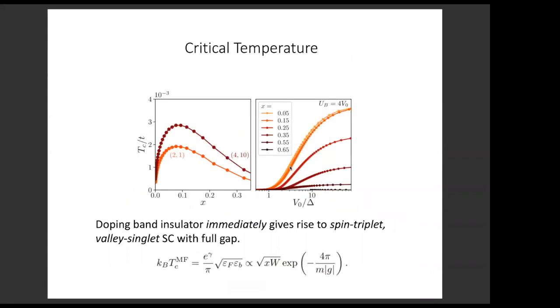So this is the prediction, and it is very striking. You dope a band insulator, and immediately a spin triplet, valley singlet superconducting state will be obtained, and this will be a state with a full gap. And the Tc again goes as the square root of doping. Okay, so next slide.